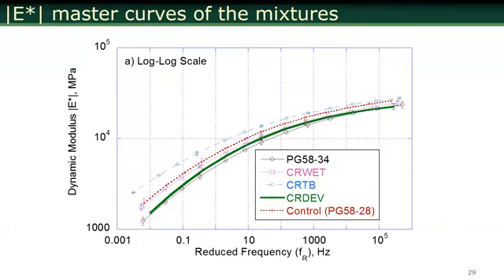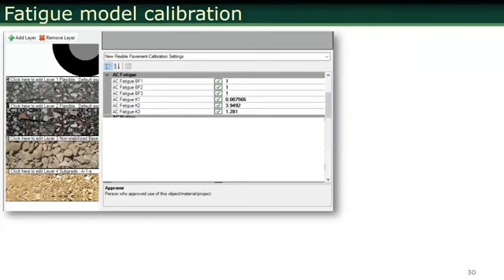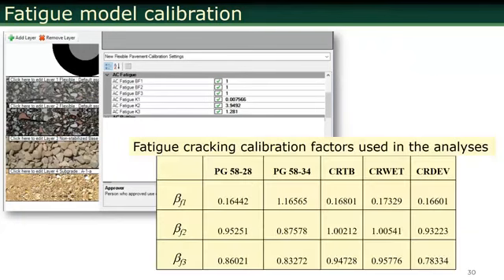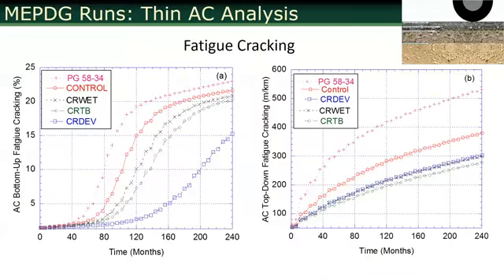So we input these in Pavement ME. We also calibrated the fatigue model for individual mixes. We ran fatigue tests for all of these mixes in the lab, and then came up with beta factors for the individual mixtures. And then we entered them into Pavement ME.